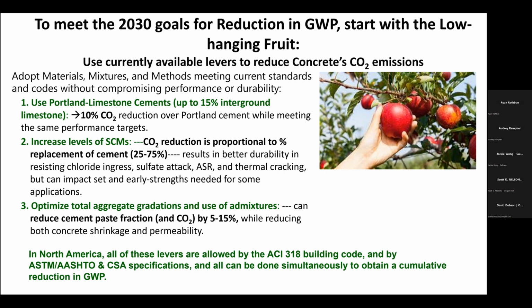Optimizing aggregate gradations. The paving industry has done a pretty good job in most places, allowing optimized total aggregate gradations, because it reduces volume change, curling and shrinkage for pavements, but it's not done across the board at ready mix. We typically have a fine aggregate spec and a coarse aggregate spec, and you can save between 5 and 15% of cement by optimizing aggregate gradations, and increase the aggregate and improve the concrete properties in terms of shrinkage and permeability at the same time. But that requires some capital investment and more bins and all that.